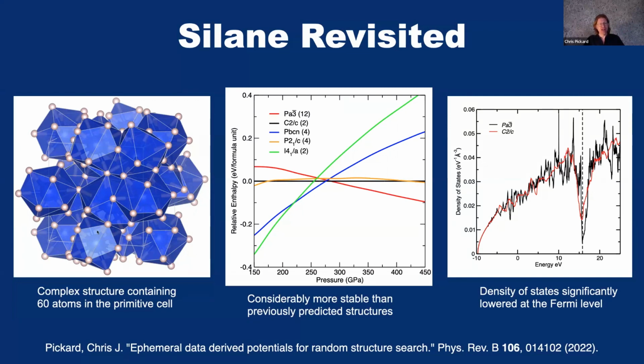On the left hand side, it has 60 atoms in a primitive unit cell. And at high pressure, it's this red curve on the center enthalpy plot. It's the most stable structure above like 275 gigapascals. There'd been a paper in, I think, Nature Communications or one of those journals, probably about 3 or 4 years ago, where they found this structure was just slightly more stable than one of my structures. And this one just blew it out of the water